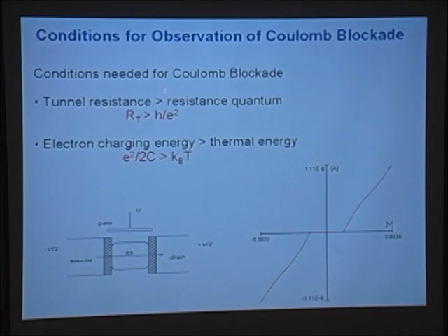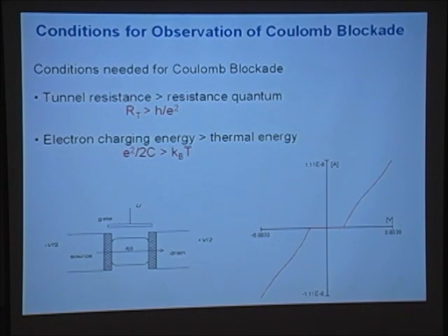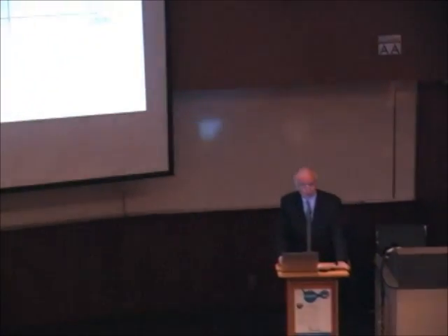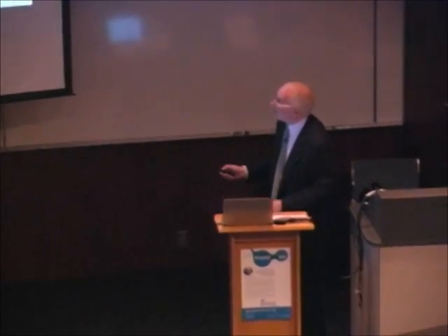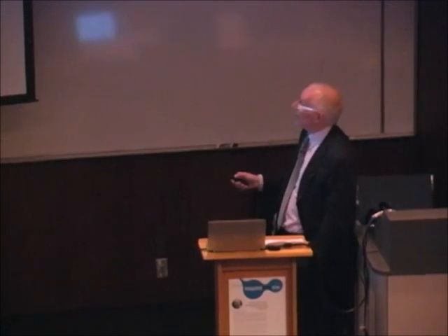This is what you see. This is the so-called Coulomb blockade, where one electron blocks others coming in. We have to have a resistance. In this case, it's a question of tunneling, but nevertheless, a resistance like that. It's an interesting example of the relationship between different aspects of the problem, because if the resistance is very small, electrons go through very quickly. If electrons go through very quickly, their energy levels can't be defined because of Heisenberg's uncertainty principle, and therefore we can't see the difference in energy due to the charging. So you need to have a high resistance to see it. And e squared upon 2C has to be bigger than kT.